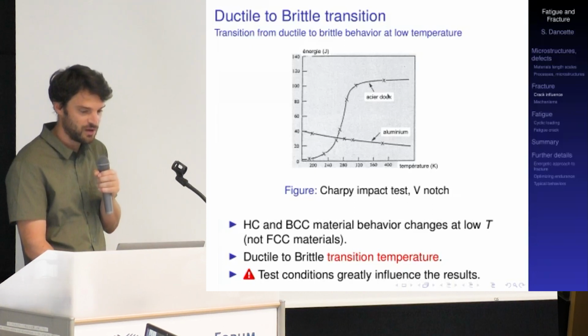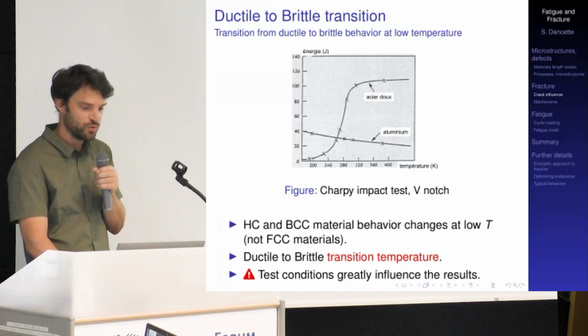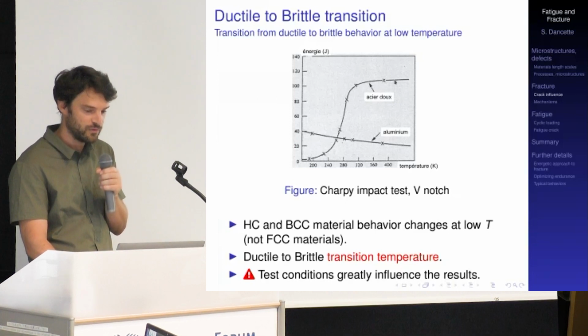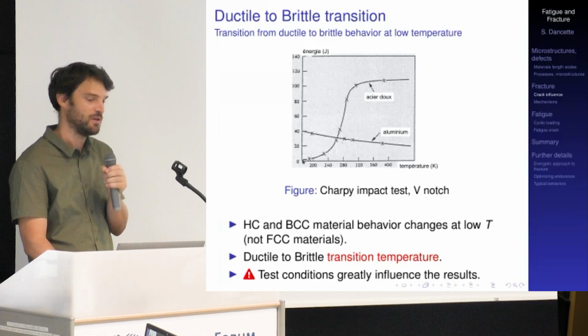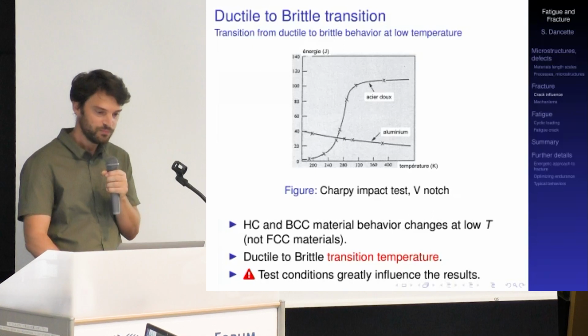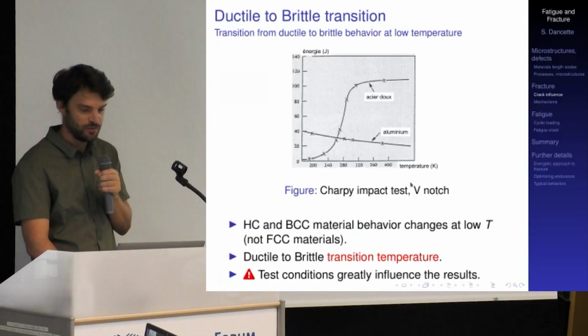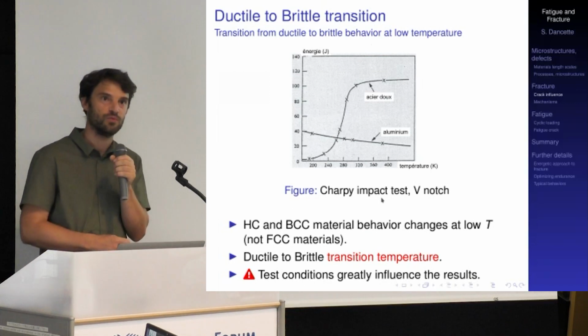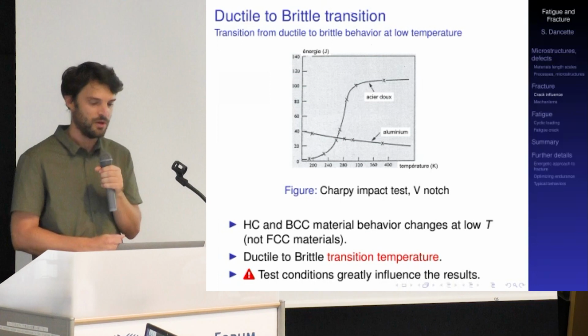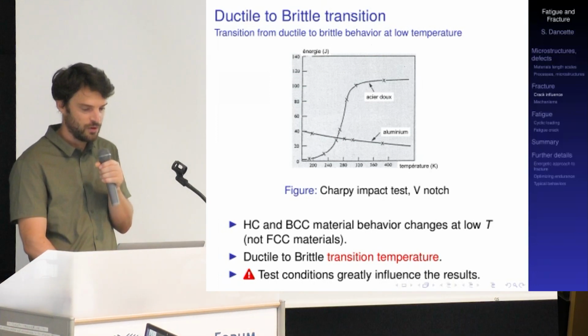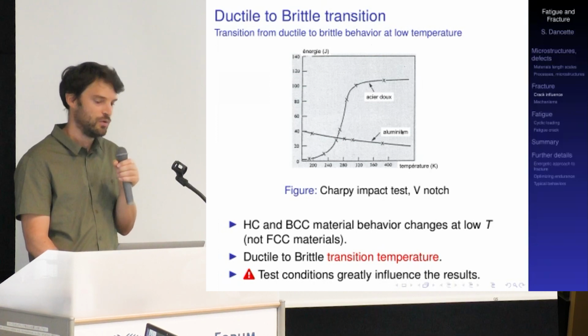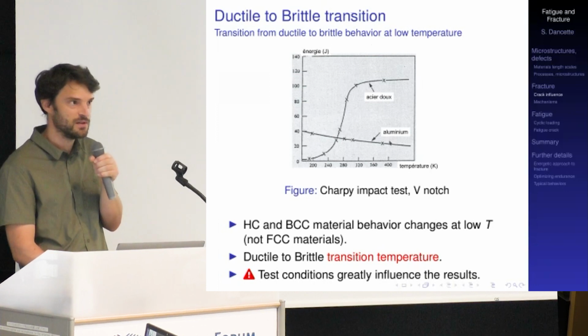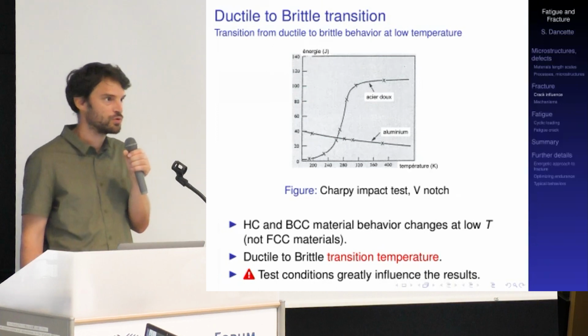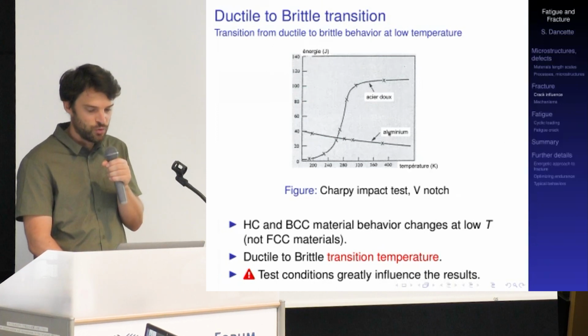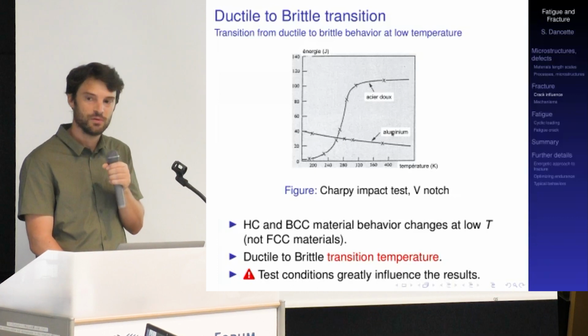So obviously, when you have a structural material like steel that shows that kind of transition from ductile, with a lot of energy, to brittle, with a very low fracture energy, this can be a problem. Okay, and with this impact test, it is quite easy, at least qualitatively, to assess the transition temperature of the behavior. You can also see here that in the case of aluminum alloys, for example, this transition from brittle to ductile is not occurring. And this is related in that particular case to the crystallographic structure of the material and to the fact that aluminum alloys are mostly face-centered cubic crystals.